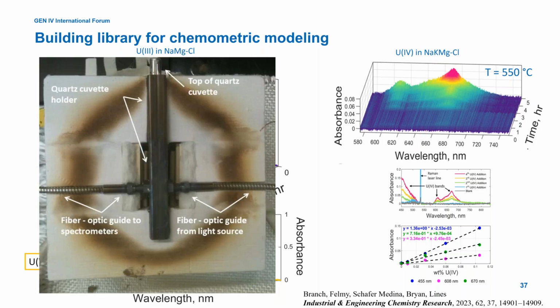And this image here shows our small-scale cuvette system that we use to measure the absorbance spectra and the Raman spectra of these salts. This shows a cutaway of our furnace that we have our cuvette within the cuvette holder shown here. We have the fiber optics, the light guide coming in and the light guide going out to the detector here. And so we have a quartz cuvette in this case, that's here. And so we can use UV vis for transmission. We also have ports that we can put Raman probes for light scattering and Raman measurements in this as well.